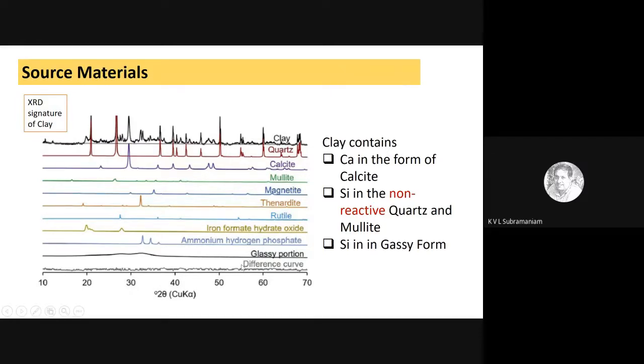Just similar to what we had seen in fly ash, the glassy part is where the silica is present in the reactive form. There's something else that I wanted to mention, and that is the calcium in this clay is present in the form of calcite, which is calcium carbonate, which I can readily use as a source of calcium. So basically, the clay is partly useful because I do have reactive silica, which is present in the glassy portion. Only it's a smaller fraction of the total silica present in the clay. And I have calcite, which I can use as a source of calcium in the system.